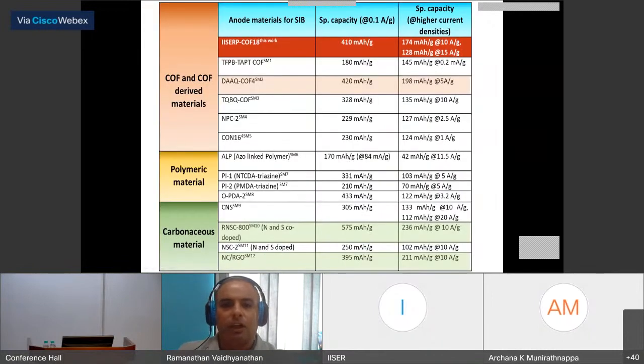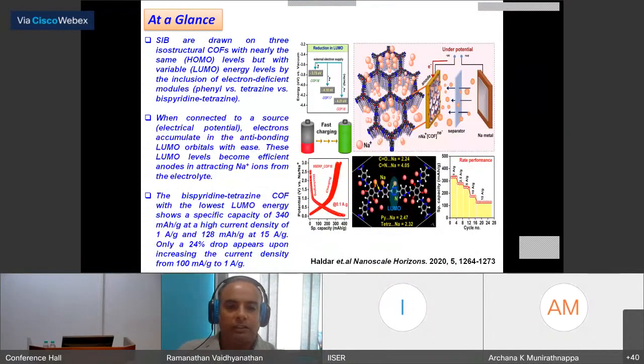So we compare it with a lot of other COFs. We stand very tall among COFs, and we have compared it with some of the best known materials, which are nitrogen sulfur doped graphene kind of compounds. So we are not too far away from them. You can see at 10 amp per gram current density, we are able to achieve 174 milliamp hour per gram specific capacity. And the value for nitrogen sulfur co-doped graphene is 236 milliamp hour per gram. So we are not too far away. So we believe there is a lot of scope in this class of materials as a sodium anode. And that is what we conclude.